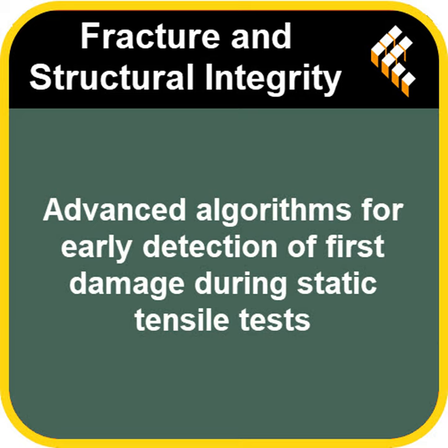Got it. Clean data first, then what? Then it divides the clean temperature data into two chunks, two subsets. The first subset starts at a fixed point in time to avoid any noise right at the start of the test, and its end point is what changes in each loop, each iteration. The second subset starts right where the first one finishes, and it goes all the way to the minimum temperature point identified in phase 2.